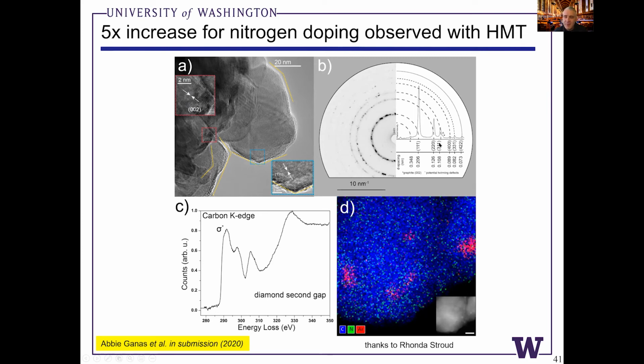One other really interesting observation that we've seen recently in the electron diffraction is just after the 311 peak for the nanodiamonds is a shoulder. And this could possibly be a graphitic peak in the sample, except we're not quite sure why its intensity is less than the 002 peak, which should have a higher intensity. We're interpreting this additional peak potentially as twinning planes and maybe even a hexagonal phase, possibly hexagonal Lonsdaleite, or at least AB stacking in the 111 direction, but possibly just a twinning plane in this material.